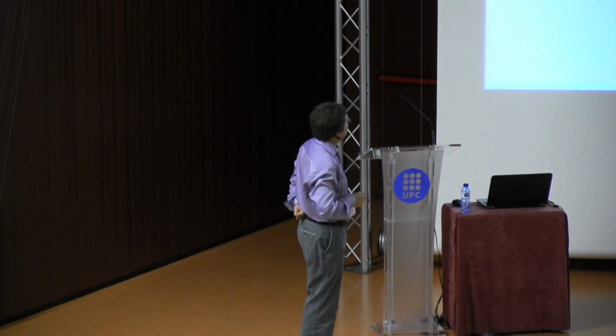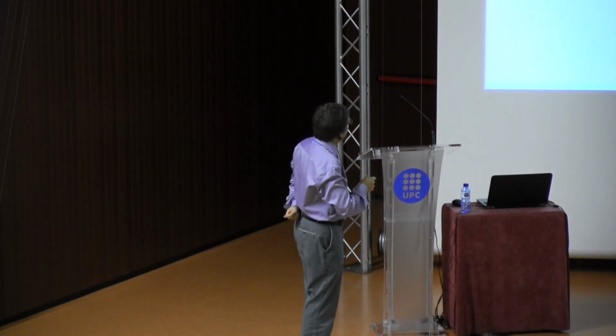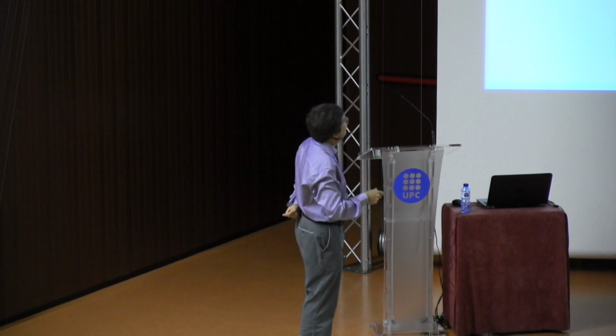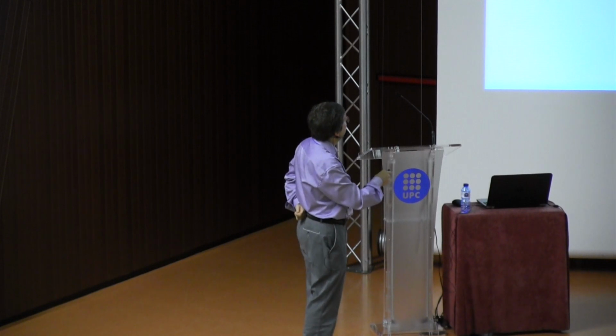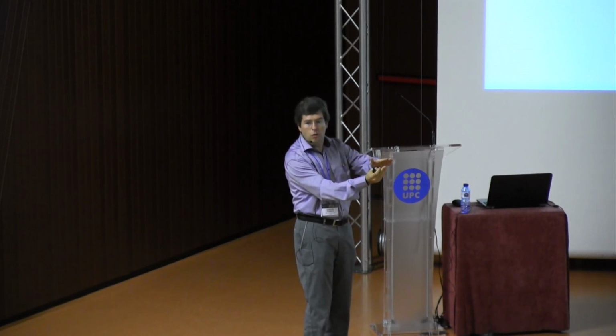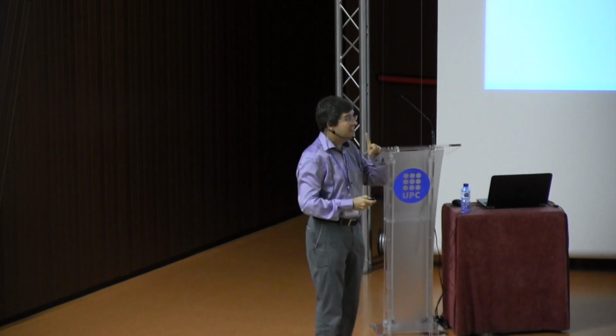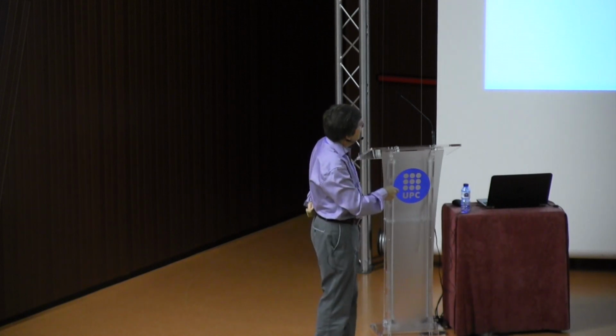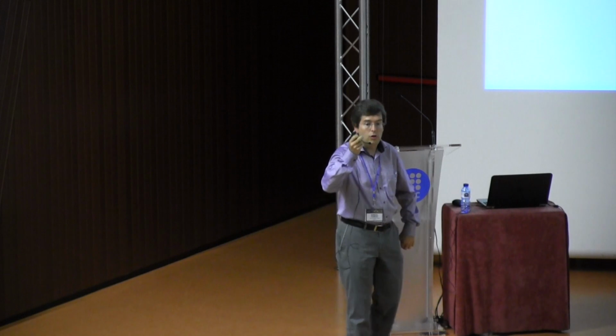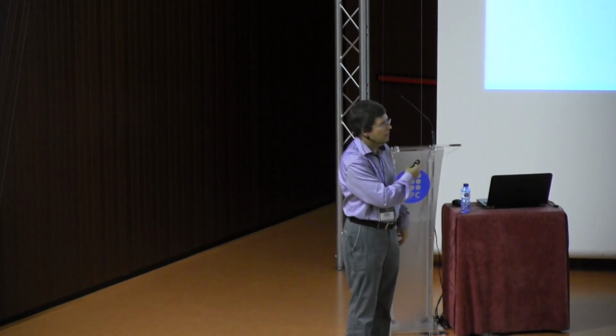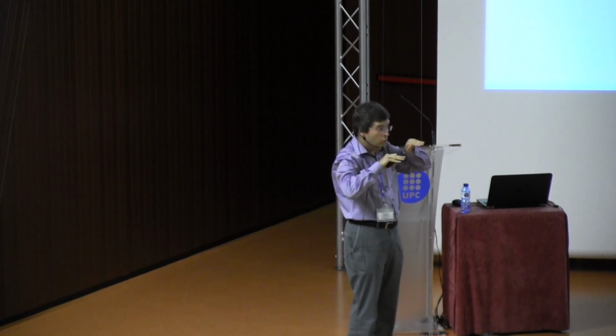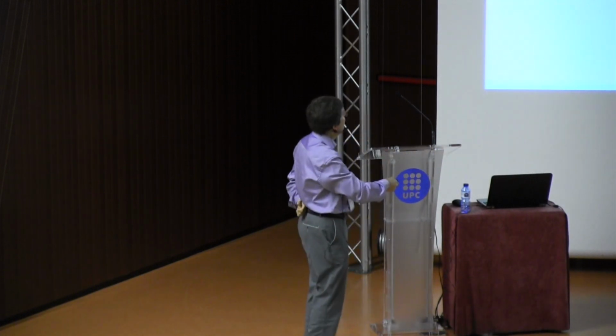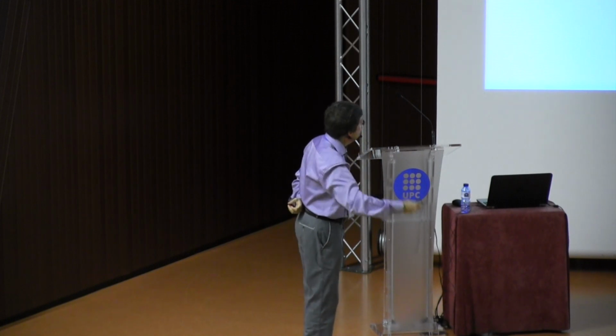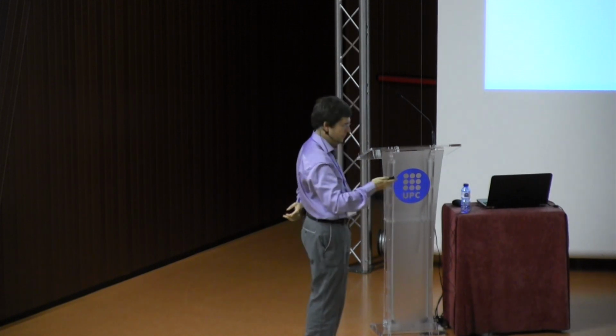For that purpose, I use a driving force, which is the normal stress to the crystallographic 1-1-1 planes. And if you reach a threshold, then I will start the damage law. But take care, once it starts, I have some linear softening, so the damage will localize, because in these single crystals, you don't have diffuse damage. You have localized damage and a crack, as you have seen on the pictures. So this is done by this softening here, which will promote localization into a crack.